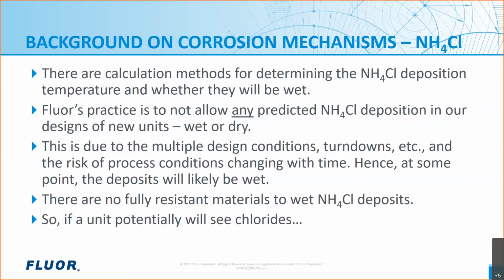But Fluor's practice is to not allow any predicted ammonium chloride deposition in our new designs of new units, wet or dry, because we feel that there's a risk. First, there's always multiple design conditions for a given unit. So we have the start of run, the end of run, then we have turn down conditions. Within all those design conditions, there's usually one that might mean that these deposits are wet. And then we also feel there's such a high risk of the process conditions changing with time. So even if initially the designs show that the deposits should be dry, at some point there's some risk that they'll be wet, for changing feeds, for changing flow rates, for some reason.